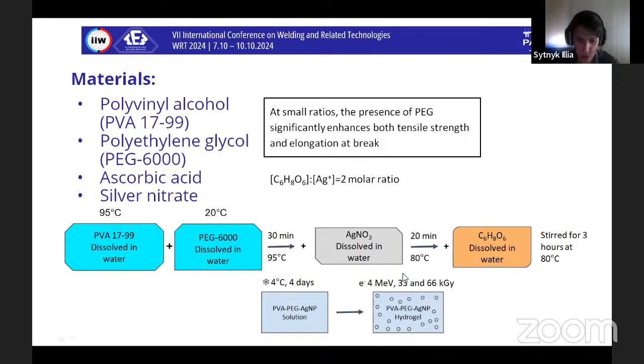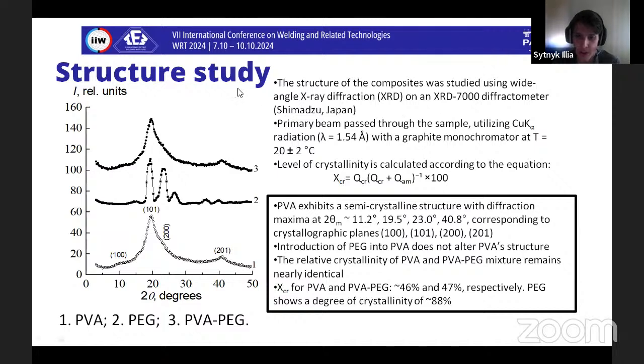The cooled gels were irradiated using a linear electron accelerator with an irradiation dose of 33 kilogray for the non-filled gel, and 66 kilogray for the silver-filled gel. The structures of the composites were studied by wide-angle X-ray diffraction on an XRD 7000 diffractometer made by Shimadzu, Japan. The X-ray optical scheme was performed by passing the primary beam through the sample using copper K alpha radiation with a wavelength of 1.54 angstrom and a graphite monochromator at a temperature of around 20 degrees Celsius.